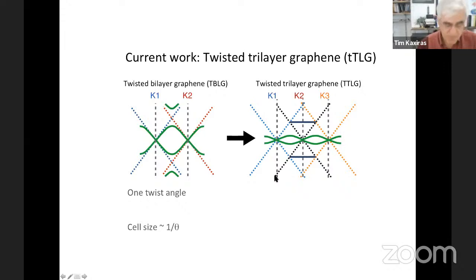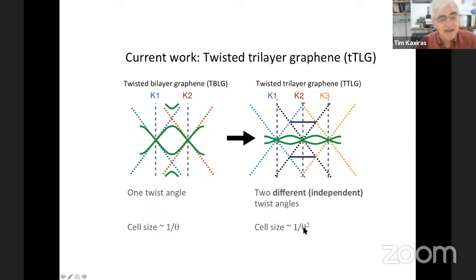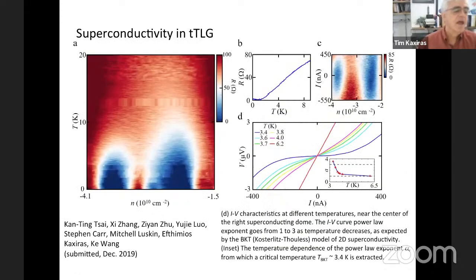Moreover, this is a much more challenging system because there are two different independent angles for the twist of the layers, the top and bottom layer relative to the middle layer, and the cell size increases as 1/θ squared because of the two different patterns. And this makes the calculations very, very difficult and quite challenging.